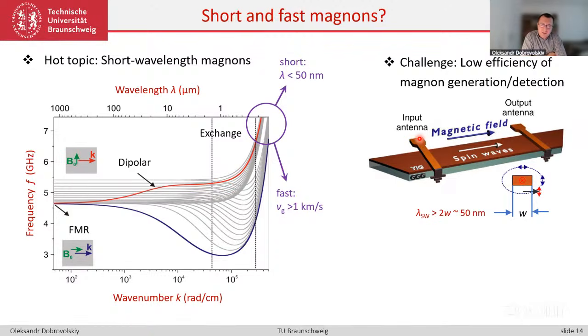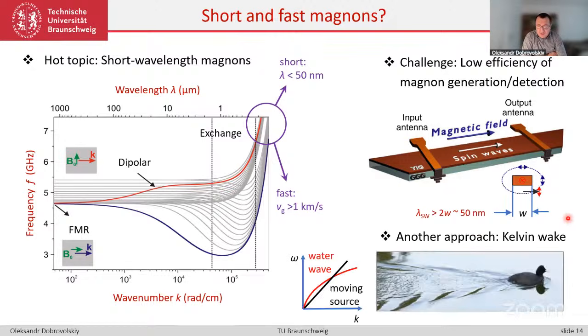This results in drastically increasing resistivity, and as a consequence of this, very high microwave losses and poor impedance matching and very low spin wave excitation and detection efficiency. So alternative approaches need to be developed, and fortunately, nature shows us further examples, and the most familiar probably is the formation of a Kelvin wake behind an object which is moving on the surface of water.